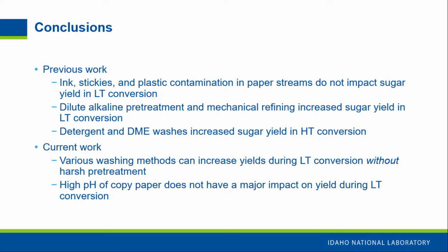So in conclusion, our previous work showed that ink, stickies, and plastic contamination in paper streams do not impact sugar yields in low temperature conversion. Dilute alkaline pretreatment and mechanical refining do increase sugar yield during low temperature conversion. Detergent and DME washing increases yield in high temperature conversion. And our current work is that various washing methods can increase yields during low temperature conversion without a harsh pretreatment. And what I mean by that is